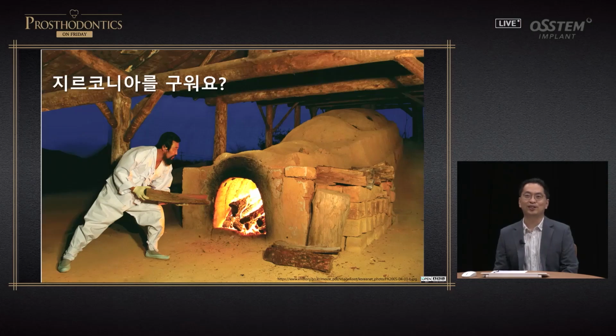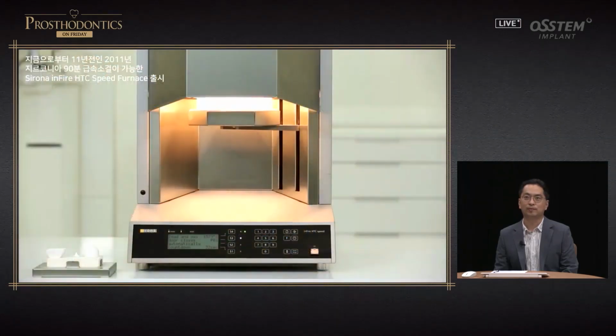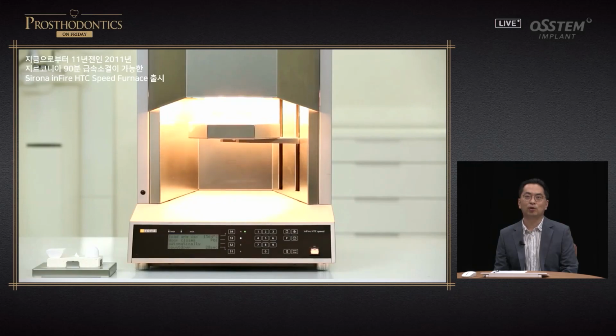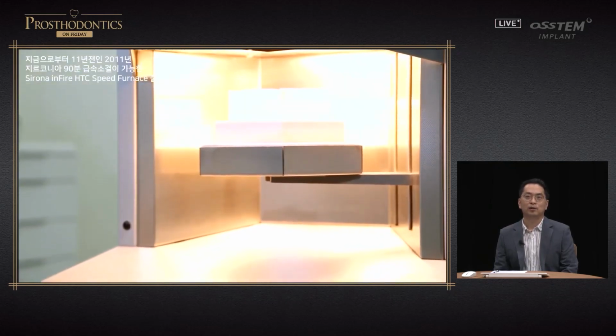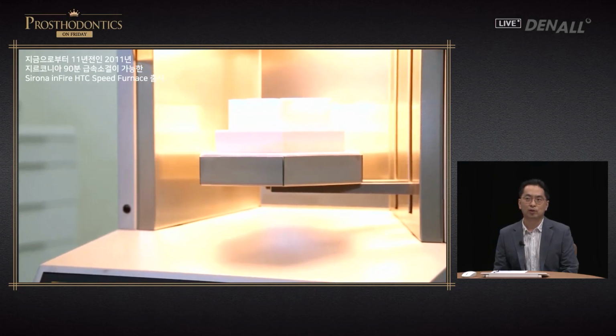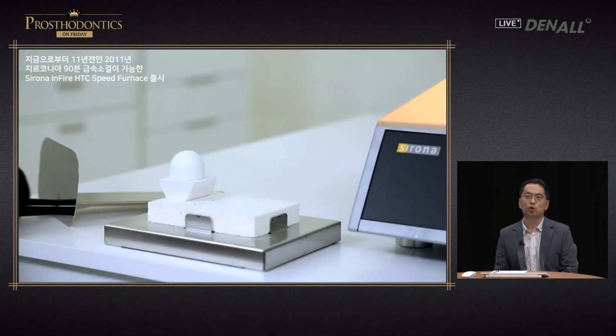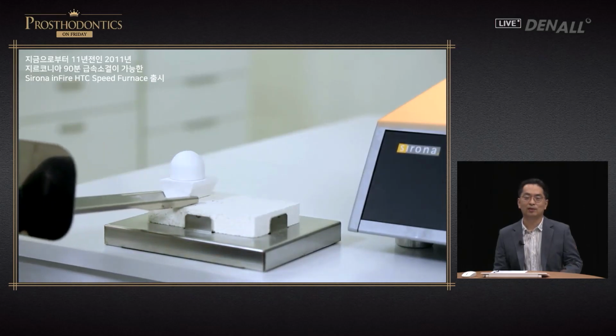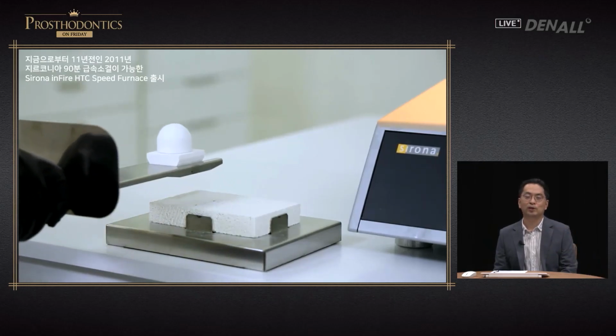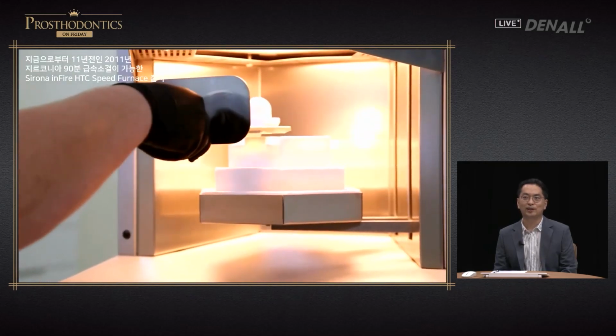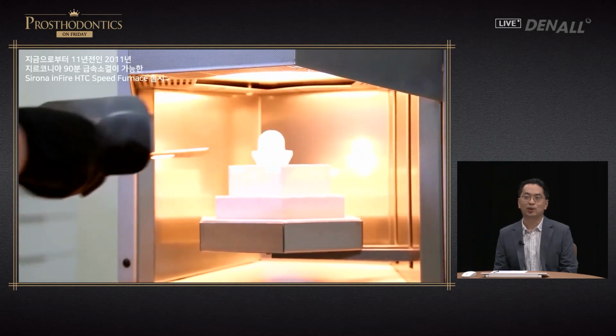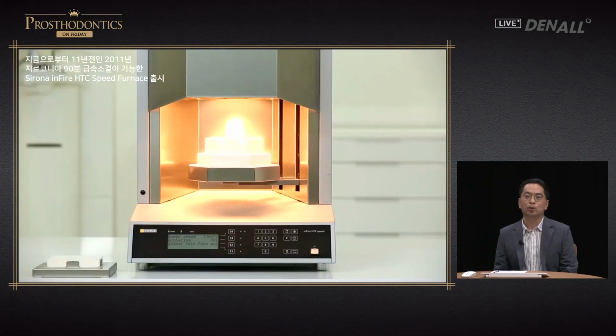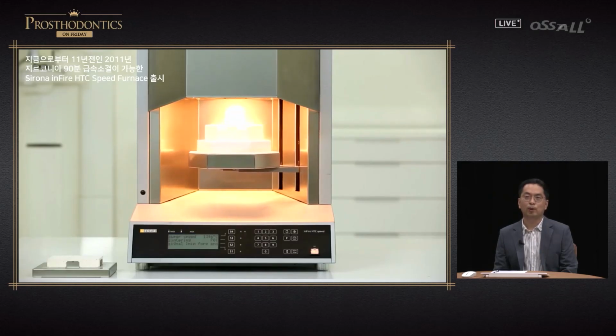Many people ask me this question: you sinter zirconia? If you have processed the zirconia yourself, you would know that through sintering process, the chalky zirconia would become hard. In order to fabricate one-day zirconia restoration 11 years ago in 2011, Sirona came up with the idea to rapidly sinter zirconia within 90 minutes. If you take a look, this is Sirona inFire HTC speed furnace. You can see that it goes up by 1,500 degrees, and as the tray goes down, the temperature goes down to 1,300 degrees. You put in the zirconia, and then as it goes up, it is heated to 1,500 degrees once again, and rapid zirconia sintering was attempted in this way.